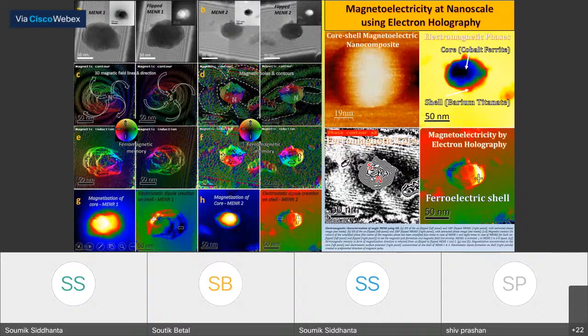Another key accomplishment of this fabrication technique is that no matter which technique we use to measure the surface morphology of this structure, we always see a similar structure, as you can see here from the atomic force microscopy image. And in the black and white phase images, you can see how the magnetic field envelope is in the vicinity of the nanoparticle and how the electric field is all confined. This electric field is confined on the surface of the structure. So we are showing magnetoelectricity at nanoscale, with all the invisible field lines made visible using electron holography.